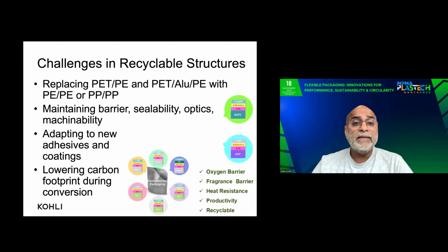Let's look at some challenges in the recyclable structure. So the traditional structure is normally polyester with polyethylene, that is PET with PE, or a polyester, aluminum foil, polyethylene structure. But now everyone is trying to replace it with a PE-PE structure or a PP-PP structure. But then they have to be careful because it has to maintain all the barrier qualities, the sealability properties, optics, and machinability. So we have to adapt to the new adhesives and coatings available in the market today. And the most important thing, again, is to lower the carbon footprint during conversion. So as you can see on the right corner down, such recyclable or sustainable materials have to have oxygen barrier, fragrance barrier, heat resistance, productivity, and recyclability.